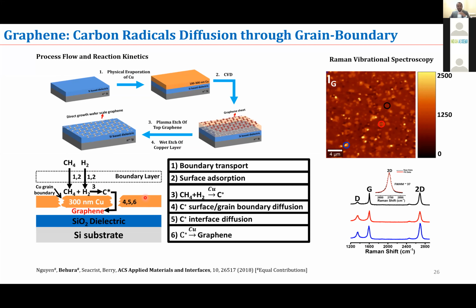And then what we can do next is to remove this copper layer, where your graphene is directly sitting on silicon dioxide. And here are Raman spectra that show the formation of graphene, because if you see a G band at about 1580 and a 2D band, which is an overtone of the defect induced D band, then you can see that this is a graphitic structure. However, if the 2D band intensity is higher than the G band, if it is double, then you can confirm that it is a single layer of graphene. So from the Raman spectra, we'll be able to confirm the graphene as well as the number of layers, in addition to other physical parameters of graphene.